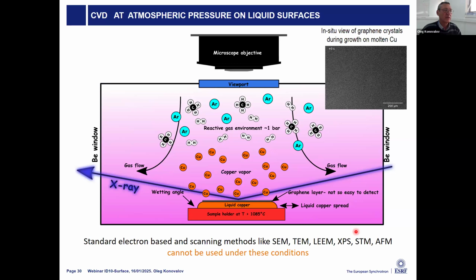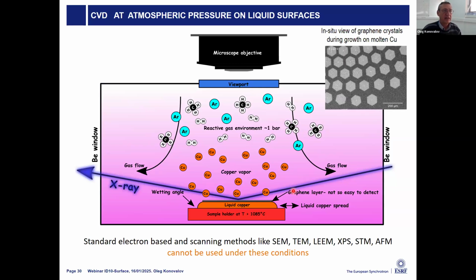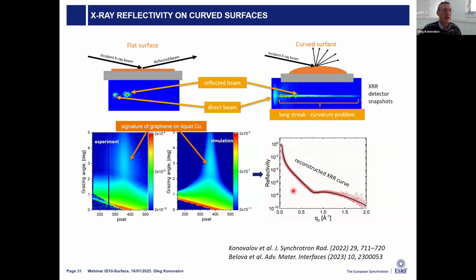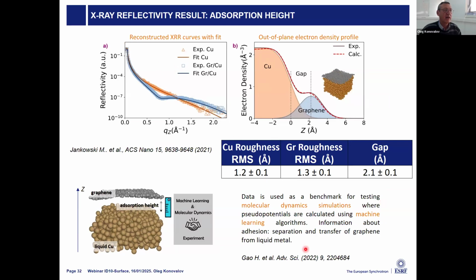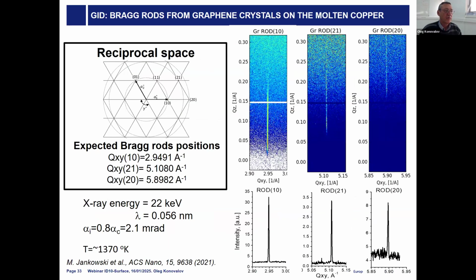Then with the CVD growth reactor that I mentioned, we can use liquid copper or other metals as a catalyst, and afterwards with different gases we can grow 2-dimensional films. On this movie, for example, you see how the graphene flakes are growing, and we see this with our optical reflection microscope. As soon as they grow, we can characterize them with reflectivity or GID. As the surface in this case is strongly curved, we found a way to analyze this anyway and reconstruct the reflectivity curves, and then get information about the thickness of these layers, the interfacial roughness, the distance between the graphene layers and the metal, and we can also measure diffraction.